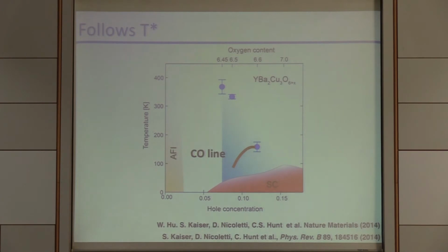Just to understand, so it means you heated up the sample to say 300 Kelvin? And this is the base temperature. Right. This is the base temperature. You're in this pseudo-gap phase, which is below this line. This mysterious, which is a gapped state with a D wave and everything, but not superconducting. And then you do shaky. Yeah, and then you see this edge, which everybody would have sworn was related to the equilibrium superconducting state, and it's at the same place where you find it in the same material when you cool below TC.